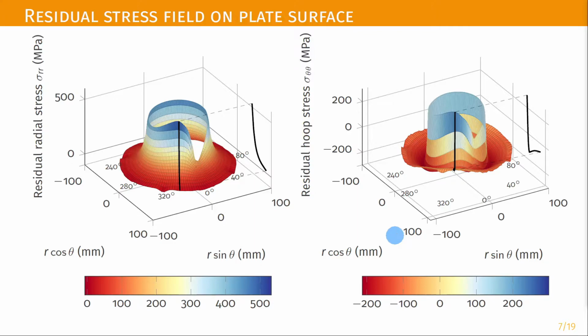The results of radial and hoop stresses are shown starting from the weld toe here up to the end of the plate. It is clearly visible a drop in both radial and hoop stresses near theta equal to 0, this angle here, where theta represents the run-in run-out point. This is precisely the area affected by the double thermal cycle, where the welding process begins and ends.